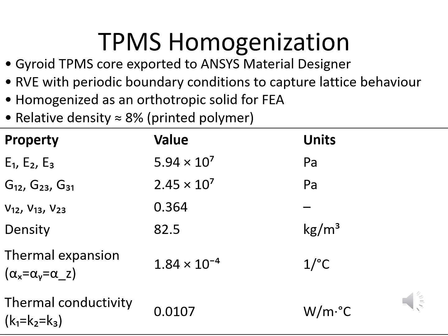To properly simulate a TPMS structure, we cannot directly run a full 3D analysis of all the lattice truss, as it would be far too computationally expensive. Instead, we use ANSYS Material Designer to build a representative unit cell of the gyroid lattice and apply periodic boundary conditions. This allows us to derive an equivalent orthotropic material, with stiffness, shear moduli and Poisson ratio, that actually represents the mechanical response of the full lattice.